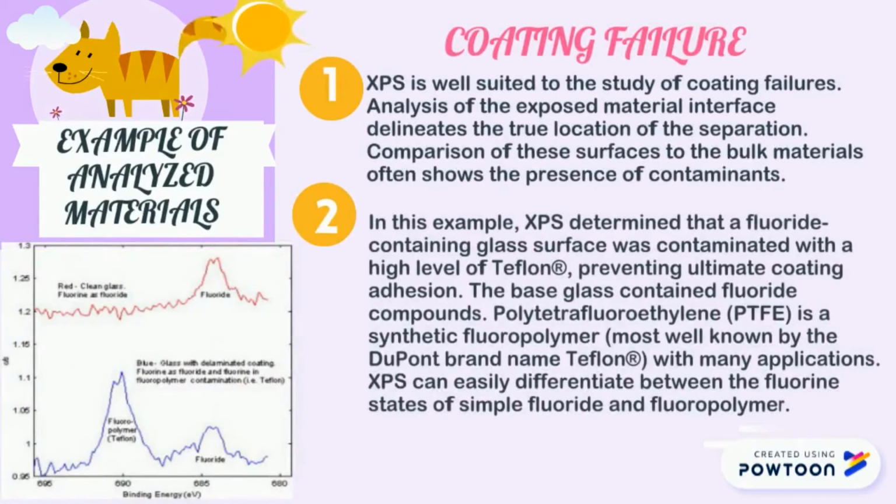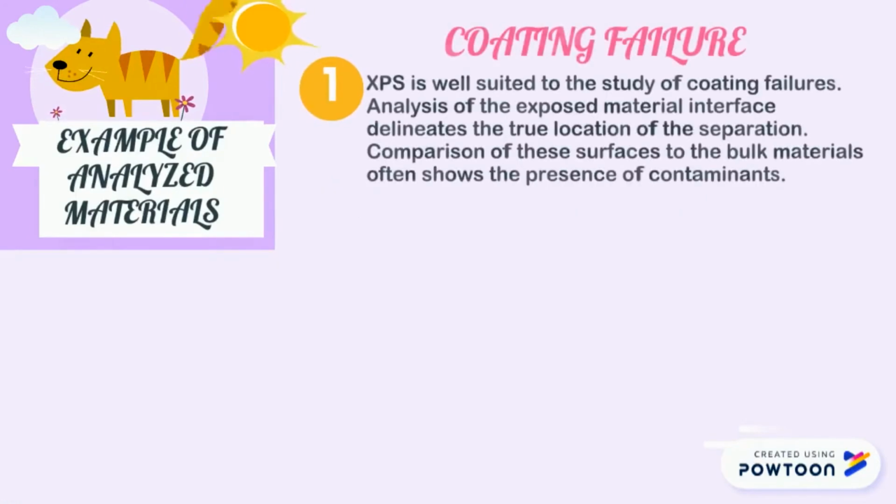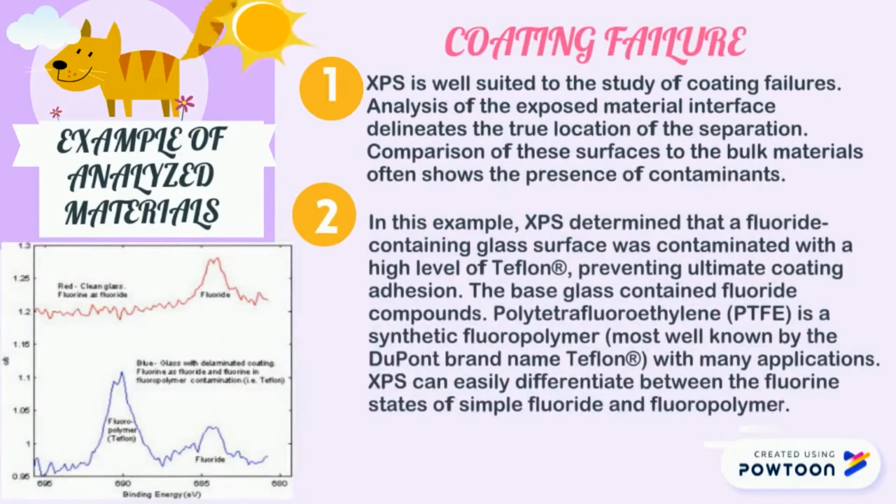XPS is well suited to the study of coating failures. Analysis of the exposed material interface delineates the true location of delamination. Comparison of the surface to the bulk material often shows the presence of contaminants. In these examples, XPS determined that a fluoride-containing glass surface was contaminated with a high level of Teflon, preventing ultimate